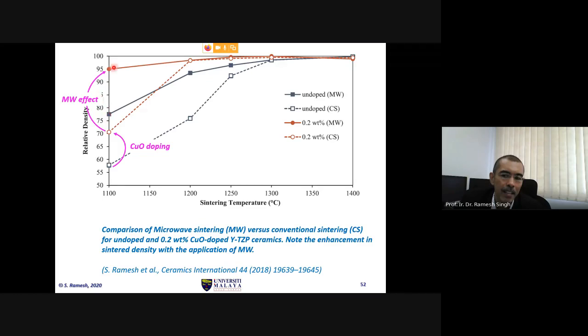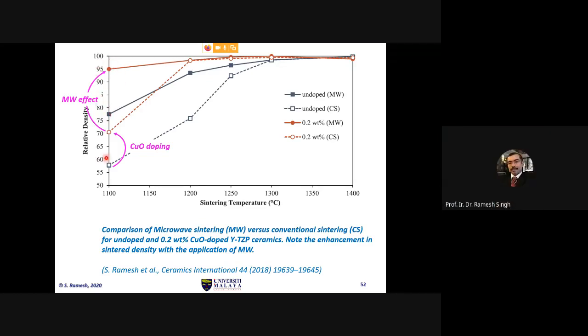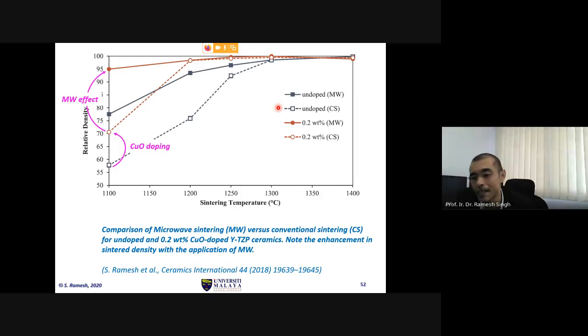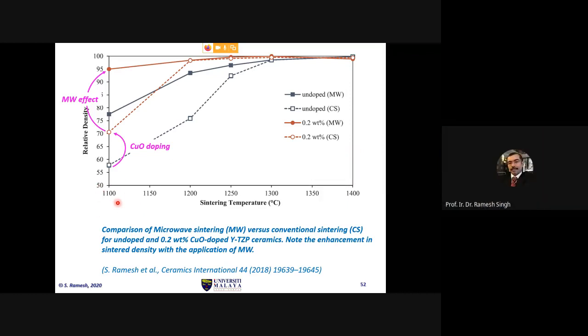So in order to reach very high densification, we first dope the material, and then we microwave the material, right? So it's a two-step approach using two different theories or ideas, right? In order to improvise the material so that we can sinter at low temperature, as you can see, at 1100. If we can sinter high density at low temperature with microwave within 10 minutes, we save a lot of energy, right? We save a lot of energy, and therefore we can make cheap component.